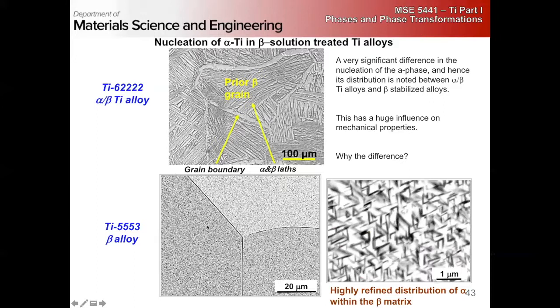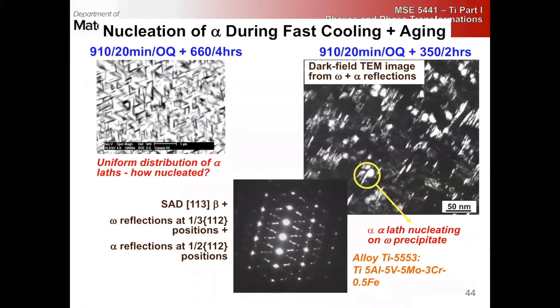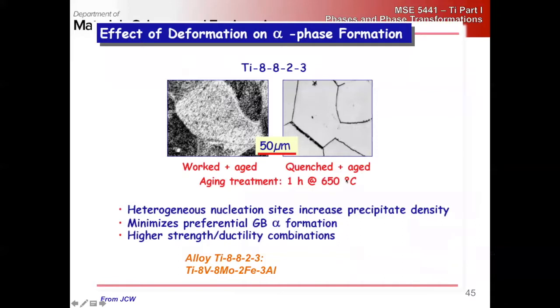In the beta alloy, we have this highly defined dispersion of alpha particles of a basket weave like structure. And again, this is what we said before. On fast cool plus aging, we get a uniform distribution of alpha laths, and this is going to nucleate from the athermal omega. Same thing that we had said before. And no surprise here, heterogeneous nucleation sites increase the precipitation density.